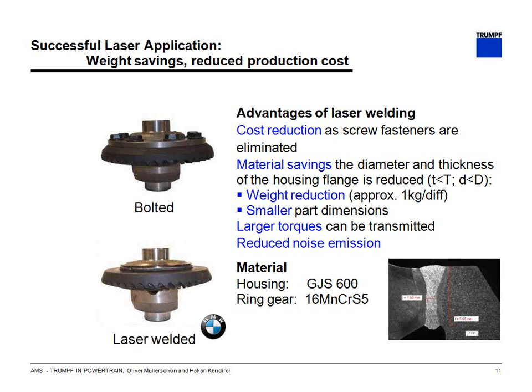At the same time, it was very important to save material in order to reduce the weight of these parts. I think it's quite easy to understand if you see these dimensions now. With the bolted version, we have a big flange here, a big diameter, and the thickness was necessary to join these parts. With the laser welded version, it's quite easy to see the thickness is thinner, and even the diameter of these housings could be reduced, so it was possible to reduce the weight here.